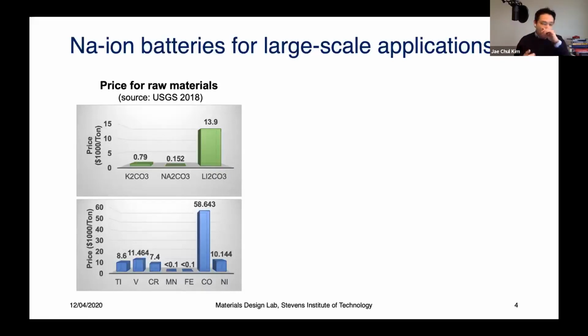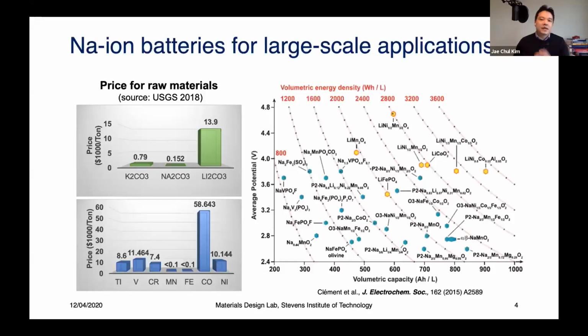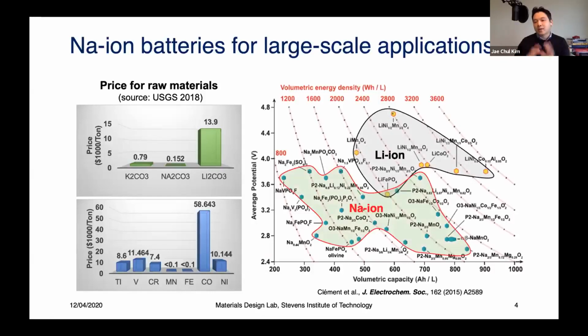Okay, so with this good perspective, why don't we use sodium ion batteries right now? Actually, the history of sodium ion batteries is as old as lithium ion. It's been about 40 years since it first came out, but there is some downside in practice. What you're seeing here is an energy density plot. Top right means you have higher energy density. And as you can see, those areas with high energy density materials all belong to lithium chemistry. Sodium ion batteries tend to have lower energy density compared to lithium in practice.